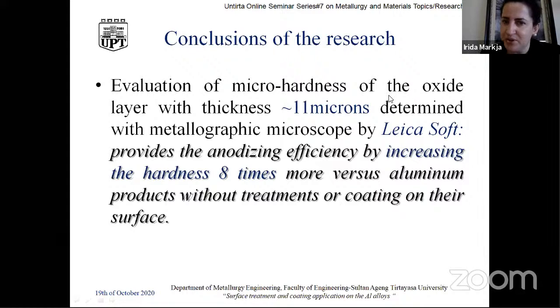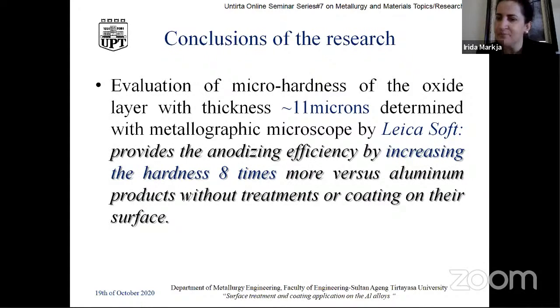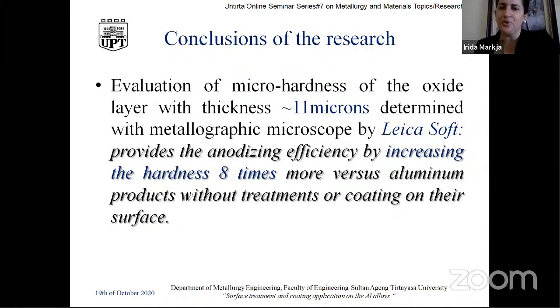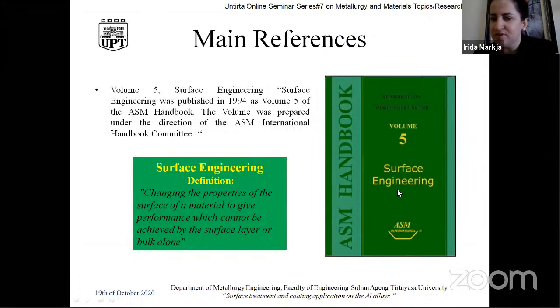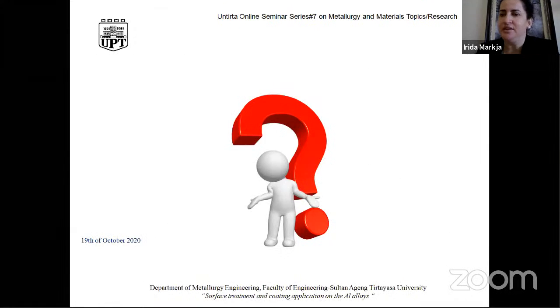Evaluation of micro hardness of the oxide layer with a thickness of 11 microns, determined by our Leica software, shows that the anodizing efficiency increases the hardness 8 times more versus the aluminum products without treatments or coating on their surface. This is the main conclusion or result of our research for the aluminum products that we have used and taken from the company in Albania. The main reference in our work was the American standard for surface engineering. Okay, I finished my presentation maybe a bit earlier than the time that I had.